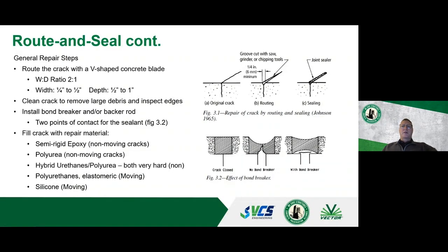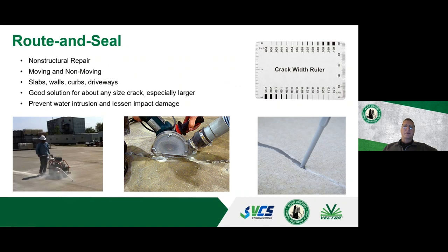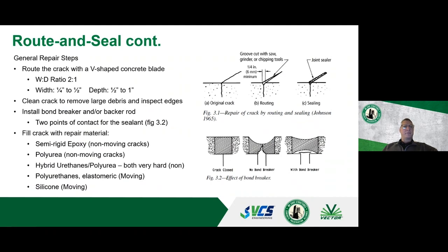So one of the pieces I want to talk about here is the routing. The routing part is where you're taking a V-shaped concrete blade, usually around a 1/4 inch, and you're expanding that crack out. And this 1/4 inch V shape that you're grinding is going to give you a consistent width, which is important for routing and sealing, because a crack by itself is very inconsistent. You can see in this middle photo, it's not the best one, but that crack is very jaggedy. You're not getting any kind of consistency. So if you're moving along and routing that out, you're going to get a consistent edge. Then you're going to come along and make sure that crack is cleaned out, the edges are clean, and then you can come back and apply your sealing material in there. And then I break down the points about the backer rod, which I talked about already.